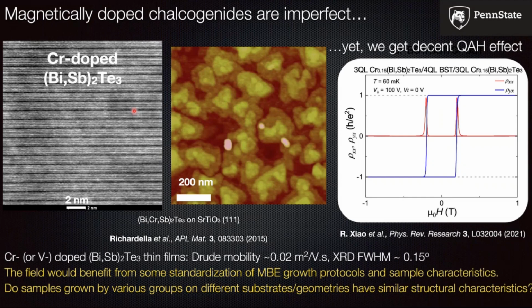The Drude mobility of the samples that we make, which provide what I would call decent quantum anomalous Hall effect, is rarely better than a few hundred centimeters squared per volt second, right? We routinely do X-ray diffraction as a way to measure the structural characteristics. And unlike the gallium arsenide samples that I make, where I can honestly say I'm making high quality gallium arsenide, here I cannot say I'm making high quality MBE grown samples.